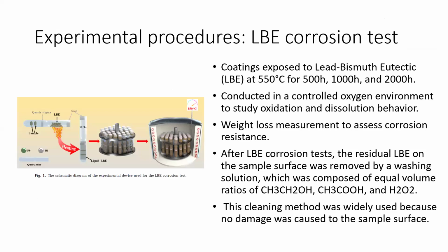So, for the LBE corrosion test, we expose the coating to LBE, like this variation. And we can see in figure 1 the schematic diagram of the experimental device used for LBE corrosion. So this is the core setup, this crucible. In this crucible, this is the sample, then this is the LBE. So this crucible we put into the